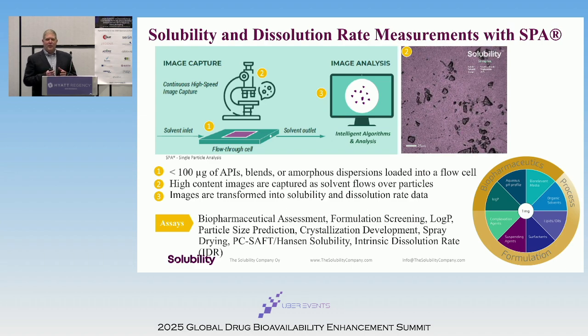So all of these images are captured under a microscope with high content imaging. And what you're seeing is basically the particles dissolving, with the video repeating over. And based off the rate at which it dissolves, it's all based on the Noyes-Whitney equation, you can then calculate what the dissolution rate is and what the solubility of that is. And there's a number of applications.